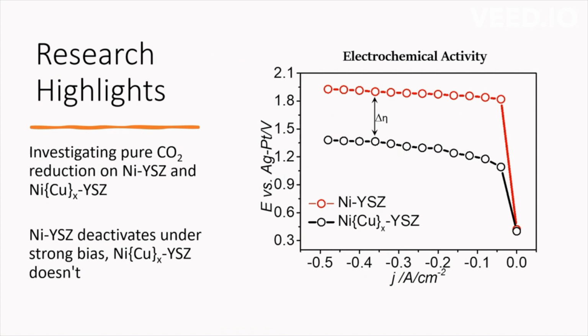Nickel YSZ electrode is conventionally used in solid oxide fuel cell as it's available commercially and its architecture is well established, and it has already been tested for long-term stability around 40,000 hours. So keeping all these characteristics of nickel YSZ in mind, this electrode is proposed for CO2 electrolysis. But when we use it in pure CO2 stream, the electrode breaks down.